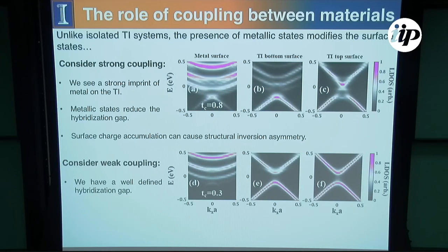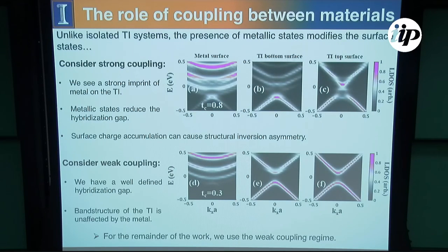The hybridization gap changes within the strong coupling region because you have some structural inversion asymmetry that causes surface charge accumulation. But in the weak coupling regime, which is mostly what we're dealing with here, the band structure of the topological insulator is relatively unaffected. But I thought that this was a particularly interesting result.